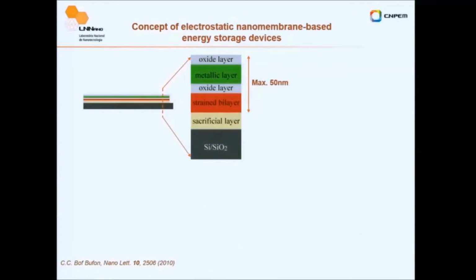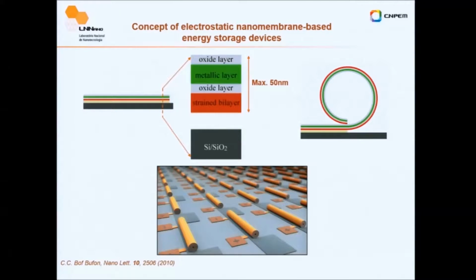So the solution was pretty straightforward. We have a sacrificial layer on top of silicon dioxide. Our first capacitor layer was our strained bilayer, and then comes oxide, and then another metallic layer, and another oxide layer. The reason for the last oxide layer is that when you start to remove your sacrificial layer to roll, the bottom metal plate touches the surface. So apart from rolling, you gain capacitance also. Basically, you have twice the area. And you can ideally create very nice arrays.